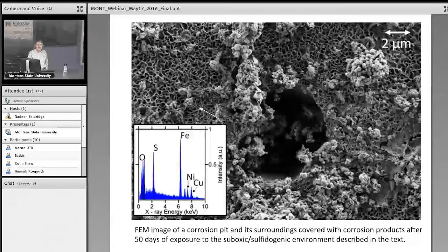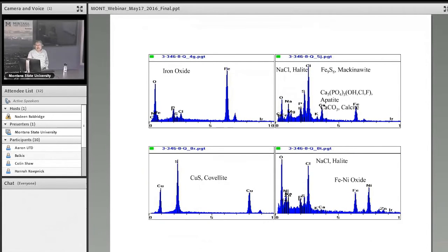And this nickel and copper is a bit surprising because we didn't know we were going to get that much nickel and copper, because the copper nickel is away from the sample, but it essentially dissolved from there and landed on the system. Well, what you do is you go very fast. You take this, what we call the EDX spectra.